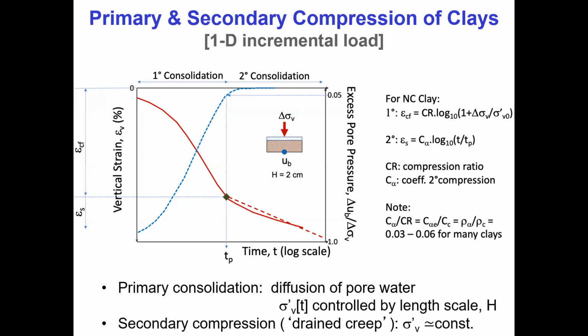If you go back to all the literature in soils, you will discover that there's a very interesting relationship between the C alpha, the slope down here, and the CR value we use in primary compression. This was first pointed out by Reza Mesri at University of Illinois. But C alpha to CR is in quite a good correspondence. Many of us use different notations. Some people use C sub C rather than CR, and C alpha epsilon rather than C alpha. The ratio turns out to be more or less the same.